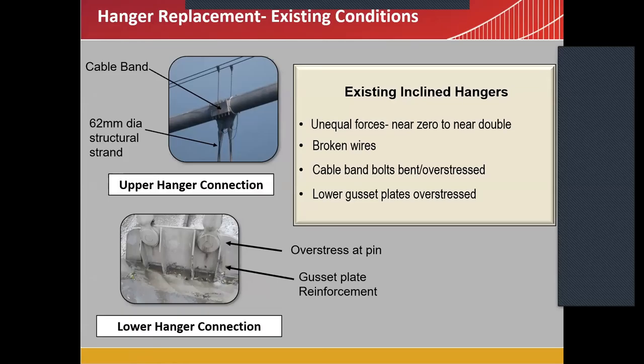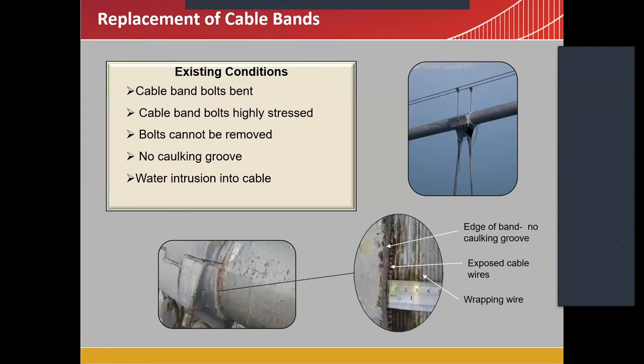The existing condition is shown in the slide, and it shows over stress at the pin, and gusset plates were reinforced with additional stiffeners. Since those are inclined hangers, the forces are always unequal, sometimes zero, sometimes exceeding the maximum capacity, and they exhibited broken wires, cable bands, bolts bent and overstress. The other problem we detected was that cable band bolts were bent and cannot be removed. There was no caulking, and water was intruding into the bands.